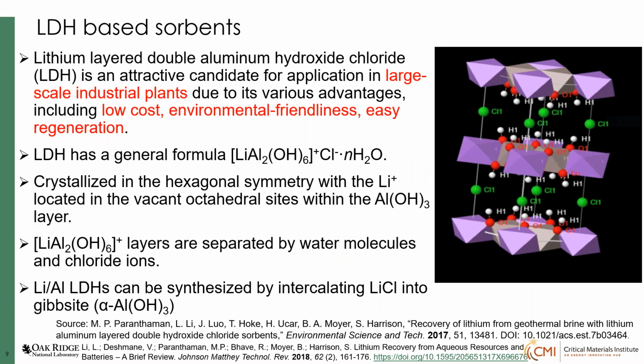Yeah, so we worked on membranes and all. This is the lithium aluminum double hydroxide structure. The basic formula is 1 mole of lithium chloride to 2 moles of aluminum hydroxide, Al(OH)3, and you have n water. This has a hexagonal symmetry, and the lithium is located in the vacant octahedral sites of aluminum hydroxide. So you have a double hydroxide layer, and lithium occupies the layer, separated by water and chloride ion. That's the structure. We published a lot of work on it.